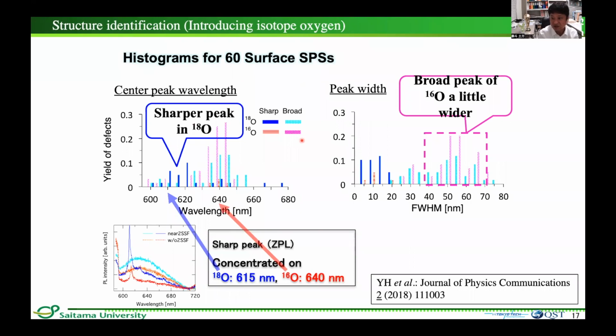These figures show histograms from 60 surface SPS for center peak wavelengths and peak widths. As we can see from the left figure, many more sharp peaks arose from 18 oxygens. Also, such sharp peaks concentrated on 615 nanometers for 18 oxygens and 640 nanometers for 16 oxygens, which corresponds to the mass difference. Furthermore, the broad peaks for 16 oxygen were a little wider, which is probably attributed to more intense phonon sideband.